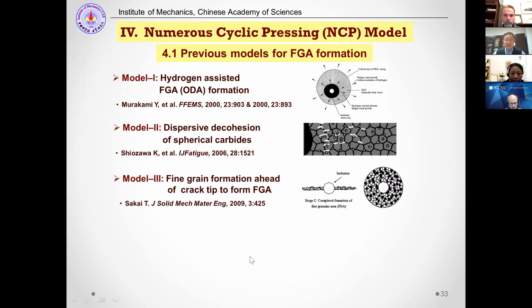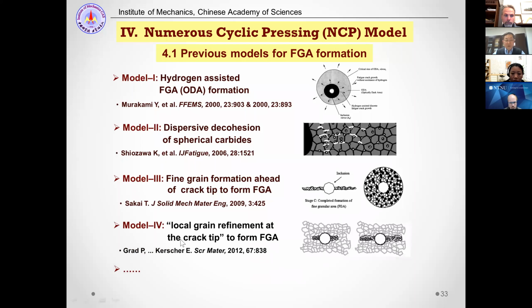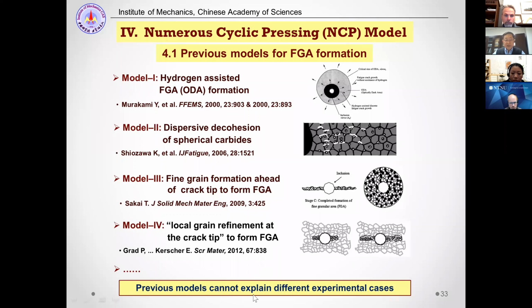And the third one is called fine granular formation ahead of crack tip to form the fine granular area, meaning that at the crack tip, the plastic deformation will induce the microstructure refinement and then the crack initiation growth to form a rough fracture surface. And the fourth one is called local grain refinement at the crack tip to form FGA. This one is somehow similar to the third one. But these previous models cannot explain different experimental cases.